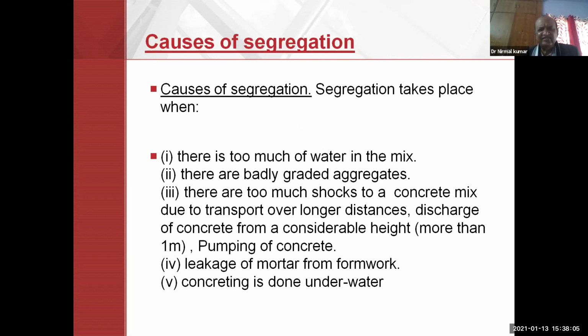The causes of segregation: there is too much water in the mix, there are badly graded aggregates, there is too much shock to the concrete mix due to transportation over a longer distance, discharge of concrete from a considerable height of more than 1 meter, pumping of concrete, leakage of mortar from formwork, or concrete placed underwater. These are the possible causes of segregation. And we have to take care of all these issues from the quality point of view.